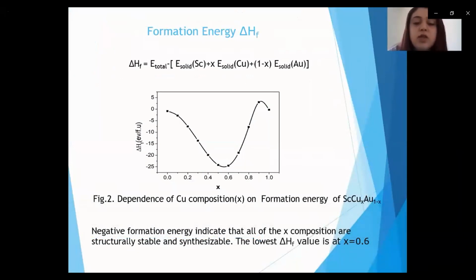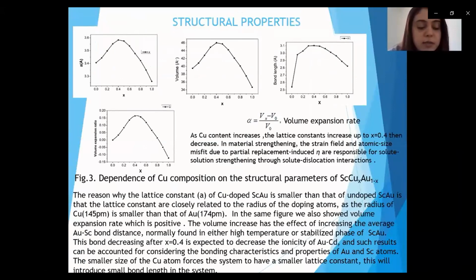Negative formation energy indicates that all of the X compositions are structurally stable and synthesizable. The lowest delta H value is at X equals 0.6. Here, you can see the dependence of copper composition on the structural parameters of scandium copper gold. The reason why the lattice constant of copper-doped scandium gold is smaller than that of undoped scandium gold is that the lattice constants are closely related to the radius of the doping atoms, as the radius of copper is smaller than that of gold. The volume increase has the effect of increasing the average gold-scandium bond distance, normally found in either high temperature or stabilized phase of scandium gold.